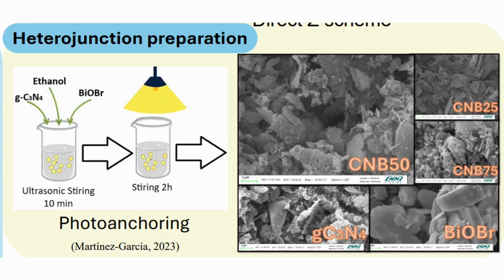The heterojunction preparation was performed with a novel simple process that we call photoanchoring. In this method, a mix of both pristine materials with the help of a photosensitizer like ethanol was dispersed in an ultrasonic bath for 10 minutes. Then, this mix is stirred with a normal stirring plate and irradiated with an LED lamp for 2 hours. This process helps us to put both materials in contact. This kind of heterojunction helps us to reduce the recombination between charge carriers and enhance the photocatalytic activity.